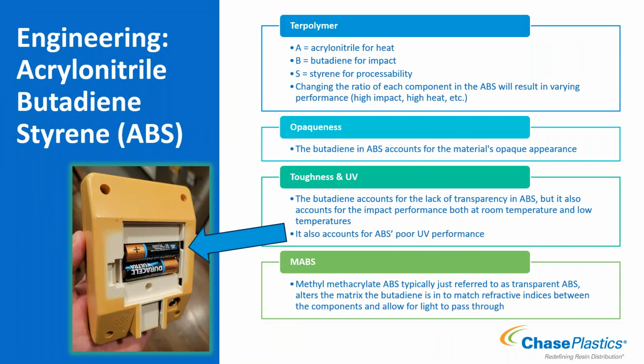It yellows very quickly. If you see the picture of a part, you can see around the batteries the color was normally more of a tannish beige color, and you can see it discolored greatly into a nasty yellowish color. That was from filtered UV light, which attacked the ABS and caused it to shift colors. That's going to happen with ABS anywhere, really, if it's outside or seeing filtered light.